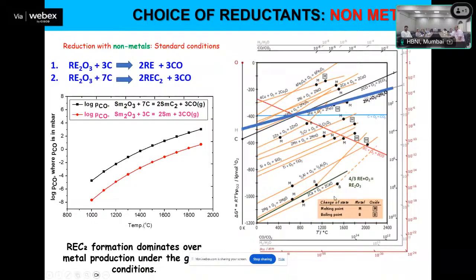If you see, rare earths almost lie below. So these cannot be reduced by carbon. Hydrogen will never reduce because this is an almost parallel line. And you can say that the carbon line is going down; at a temperature of 2000 degrees it will definitely intersect. Then why can carbon not be used? Because we did this calculation, and there is one more competing reaction, rare earth carbide formation with CO evolution. So these two reactions will be there.